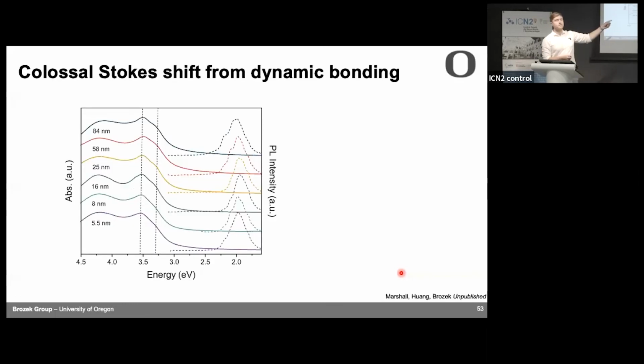They also fluoresce. So here are the UV vis spectra. You see there's a slight redshift as you change the size, but the luminescence is in the dash data. There's a huge shift in energy, change in energy between. So, we would call this a really big Stokes shift. Normally, the energy that something fluoresces should be really similar to the energy where it absorbs. But here, there's a redshift of about 1.5 eV.